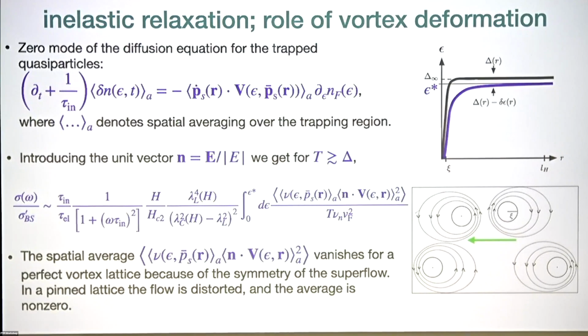So this angular brackets denote spatial averaging at a given energy in the trapping region. And so you can see that if you put this far field contribution where this condensate acceleration is proportional to the electric field for a symmetric vortex, this average vanishes and you don't get inelastic relaxation. But in the presence of pinning, vortices are distorted, and so this term does not vanish, and you do get a contribution to the conductivity proportional to the inelastic relaxation time with these similar coefficients.